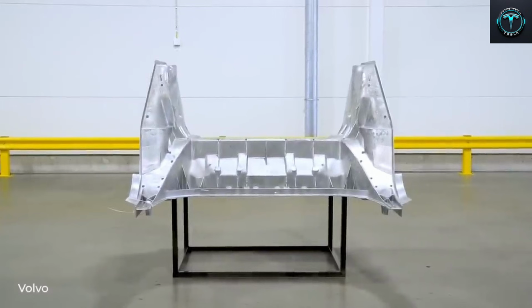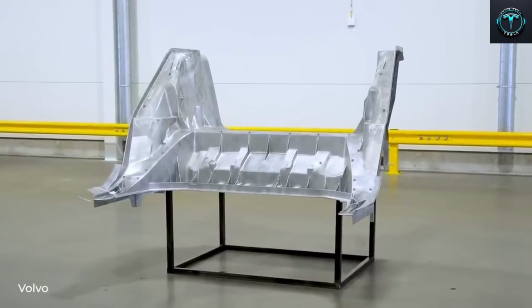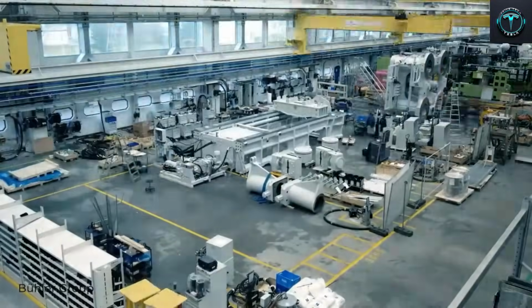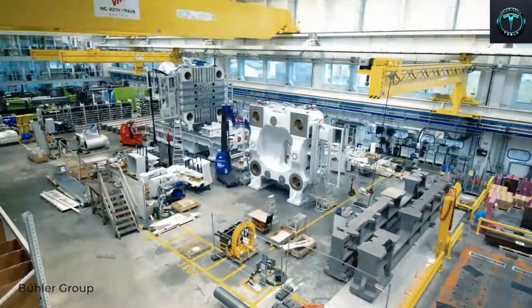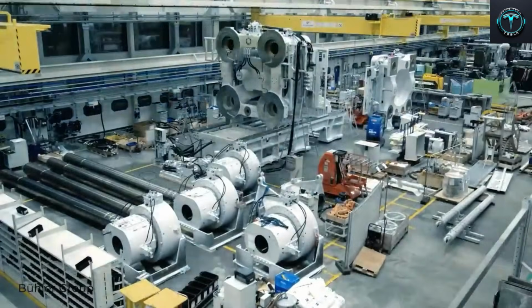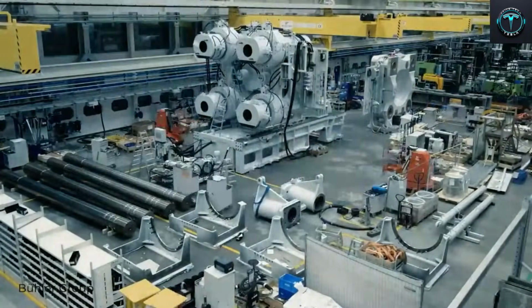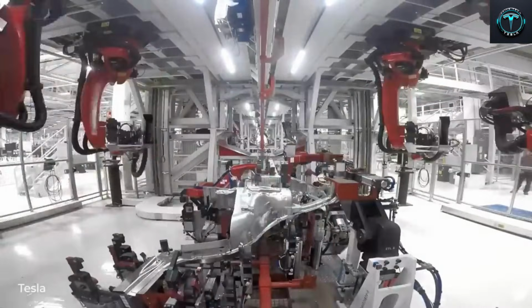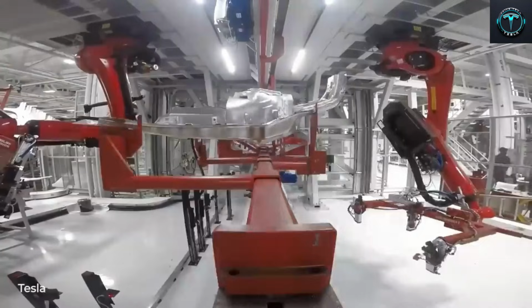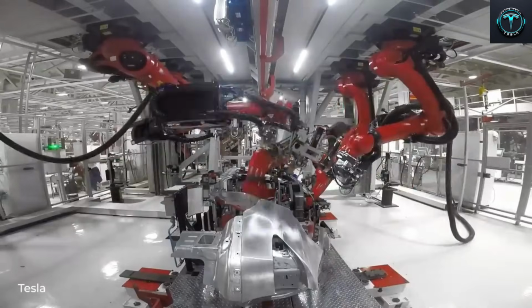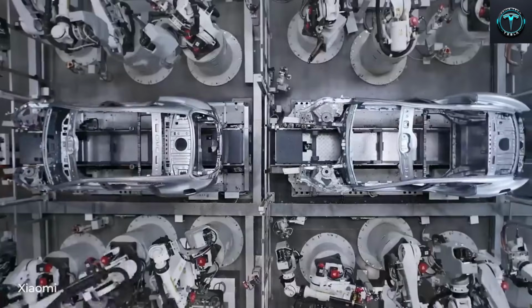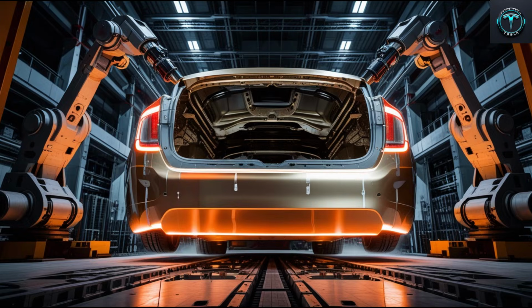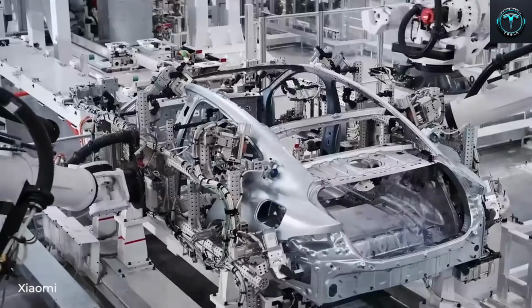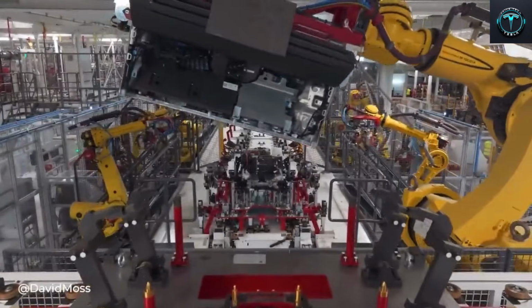The process begins with material preparation, and even at this stage, the level of engineering involved is remarkable. Fresh aluminum ingots are combined with recycled scrap from previous casting runs and melted together in a furnace operating at around 850 degrees Celsius. Once the surface impurities have been removed, the liquid metal flows through heated pipes into a second sealed holding furnace, which maintains the alloy at a precise temperature between 750 and 850 degrees Celsius. This dual furnace setup is critical. The first furnace handles the melting, while the second acts as a temperature-controlled reservoir that keeps the metal in exactly the right condition for injection.